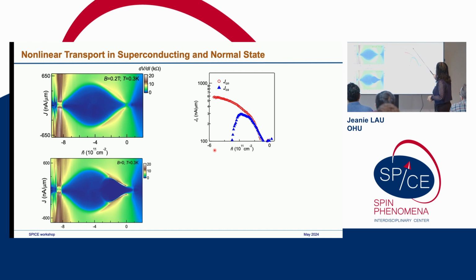I'm going to call this a critical current, where the peaks are. In the normal state and the superconducting state, I'm going to plot the same graph. Now we can see it looks like this. This is the normal state, in red, and this is the critical current in the superconducting state, which is following this structure here.